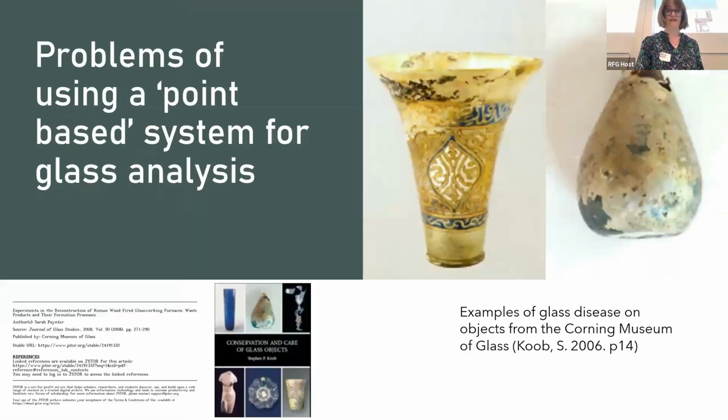So, as demonstrated by the diagram I've forced you all to look at, glass is not a crystalline structure and is therefore highly vulnerable to leaching and weathering post-deposition, which can lead to changes in composition, color, and iridescence. As the previous slide discussed, recycling can complicate the composition of the glass vessel, which could lead to weakness in the structure of the glass and an increased likelihood of the glass developing something called glass disease, which is a process of deterioration that leads to the formation of shiny deposits on the surface of glass and will lead to the disintegration of the vessel over time.